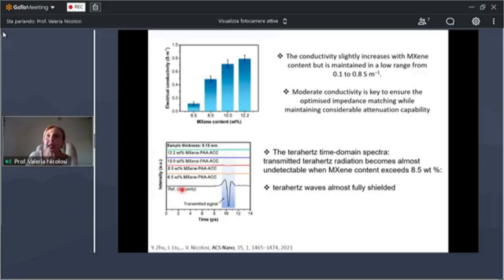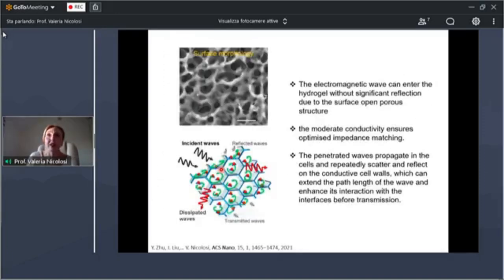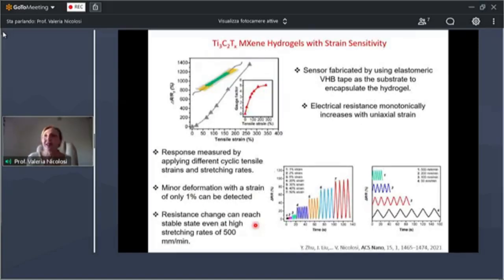Here is, for example, a terahertz signal when the hydrogel doesn't have any MXene, but with only 6.5% in weight of MXene in the hydrogel, we can already screen most of the radiation, and with 8.5% in weight of MXene, you get a full screening of terahertz radiation, which is very, very efficient. The reason is because of the cavities that we have in these hydrogels. So the radiation goes in and it is scattered repeatedly until the transmitted waves are basically totally screened.